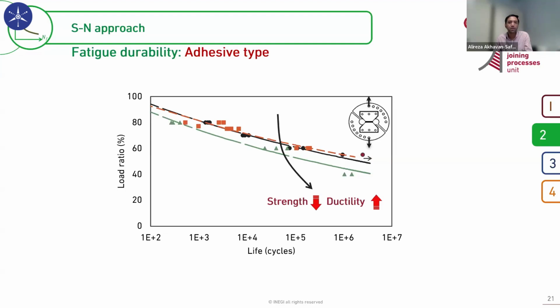If it's SN based, and if it's a brittle one, then of course the maximum tensile strength. And in case you are talking about a load control scenario, in case the joint is subjected to displacement control, then probably the stiffness can be the most important one, because you can simply reach the final strength or limitation of the joint.